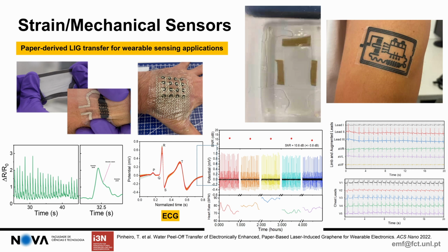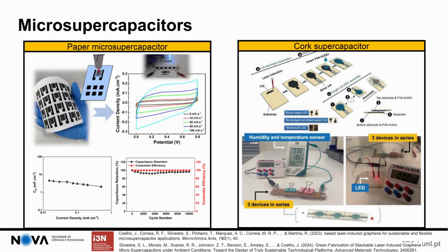And here it's quite interesting because we are just using office paper, and we induce the graphene layer on top of the paper. After that, like a tattoo, we detach the graphene layer onto another, very thin membrane, in order to have a very high resolution pressure sensor that we can touch on our skin. So here are more examples.